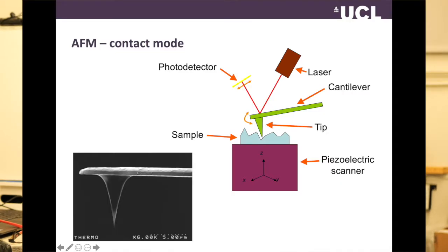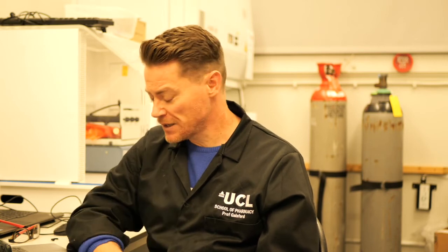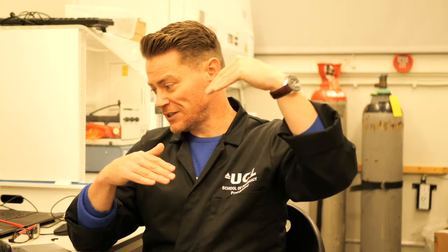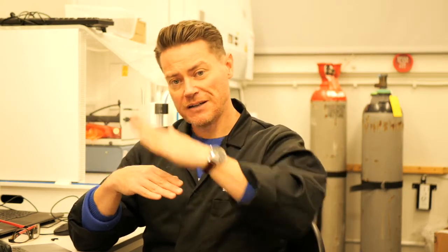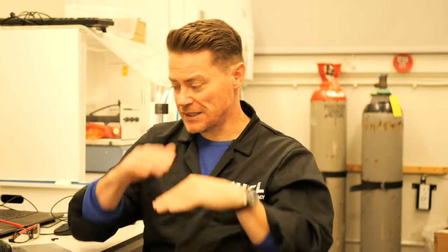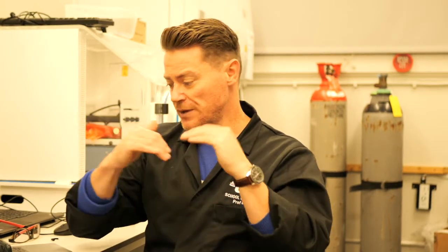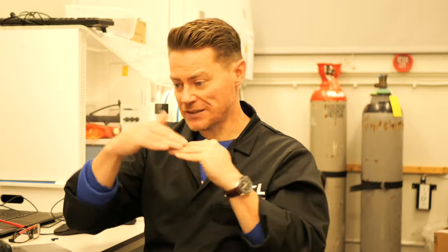This is just a diagram to show you in principle how this works. The image on the bottom left is an actual SEM image, so you should be able to tell by now because it's grayscale. It's an SEM image of the tip of the microscope. You can see it's a very fine tip, almost like the needle on a record player, for instance. And then on the right hand side it simply shows you a schematic of how that's working. The tip's moving across the sample, the laser is shining onto the back of the mirror, is being reflected and is being detected, and you move the tip across the sample in an XY pattern and measure the Z.